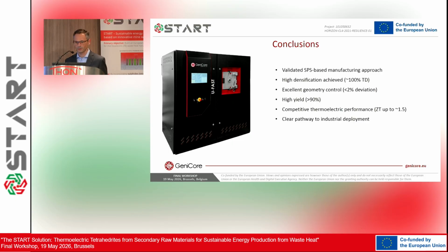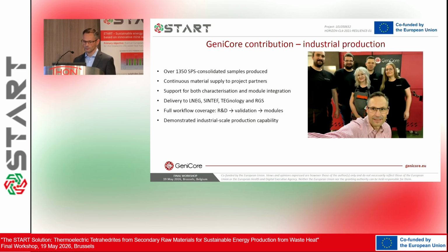Still, we don't know which factor of the process is responsible for this. Maybe a little bit different cooling stage because of the bigger mass of the system. Some numbers: over 1,300 samples were consolidated through the process. We heard about the kilograms, which is around 10 kilograms of sintered materials, probably around 30 different compositions.